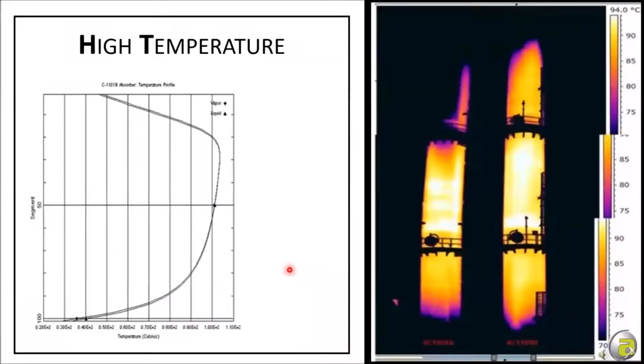This is a particular client that couldn't meet spec. This is a CO2 removal facility. It's for an LNG facility. And they could not meet spec. When I ran the simulations, this is the simulated temperature profile. We don't like to have amines above 85 degrees C because they have the potential to liberate acid gas. And then obviously at high temperature, they also don't want to absorb CO2 or H2S.